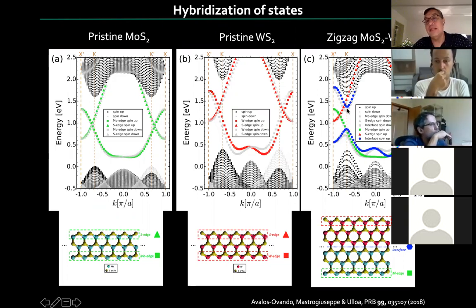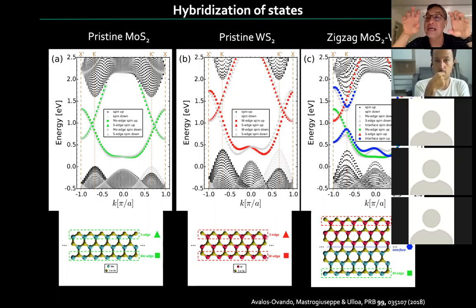And so by making this interface, you can see that you created a new gap in the material. So it will be a different semiconductor, where these states live at the interface and as a consequence will inherit properties from the two materials. So it's kind of an interesting object.